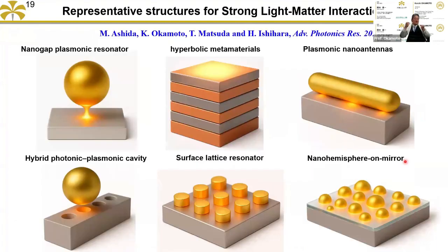So the important thing is how to obtain very strong coupling of the light and the matter. Many people proposed many structures, for example, using nano gaps or such multiple layer structures of metal and dielectric material, or plasmonic nano antenna structures, or hybrid photonic and plasmonic cavities. Or that one is the surface lattice, a very aligned lattice structure. By using this alignment, people can enhance the resonance. But our newly proposed method is based on a very random structure, but the metal is there. That's why we call that the nanohemisphere-on-mirror structure.